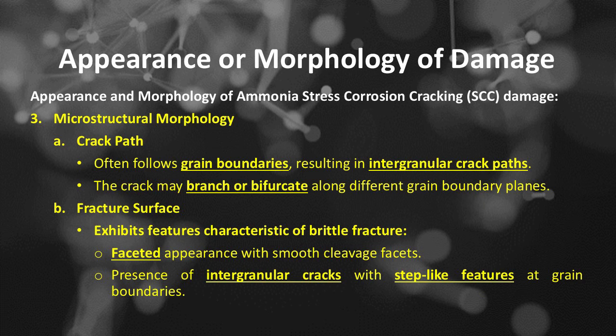Appearance and morphology of ammonia stress corrosion cracking damage. Number 3 is microstructural morphology, includes, number A, crack path, often follows grain boundaries, resulting in intergranular crack paths. The crack may branch or bifurcate along different grain boundary planes. Number B, fracture surface, exhibits features characteristic of brittle fracture, faceted appearance with smooth cleavage facets, presence of intergranular cracks with step-like features at grain boundaries.